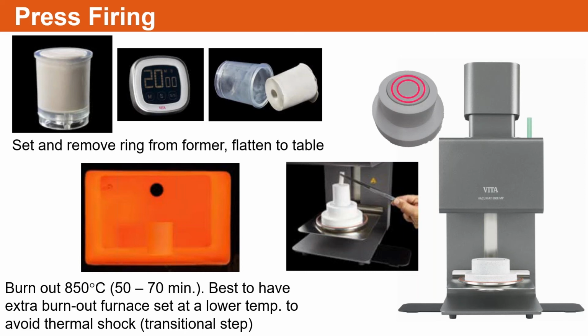And I can tell you, being in enough laboratories that do hundreds of pressed rings every day and have multiple press furnaces, the one thing they all have in common is that they have an additional burnout furnace of a lower temperature. They go from the investment stage, remove the muffle, and then take the ring without the muffle and put it in this lower temperature burnout furnace, maybe around 650 to 700 degrees. They maintain it in there for 20, 30 minutes. Then they move it over to the correct burnout furnace to achieve that 850.